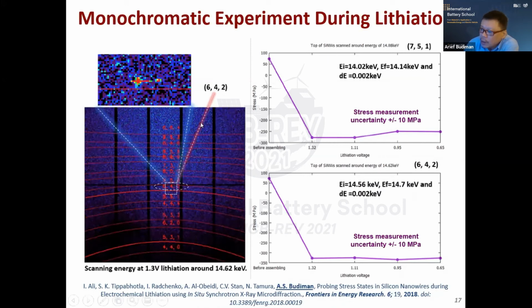Okay, so here it's an X-ray diffraction. So you will see the HKL here, all the polychromatic rings, the crystalline rings of the silicon nanowires. So we know that the stress develops such that at first it is a tensile stress, and then it starts to develop more and more compressive stress. So this is good news. Good news is that we talk about cracks. Cracks don't happen in a compressive stress state. Cracks only happen in a tensile stress state.